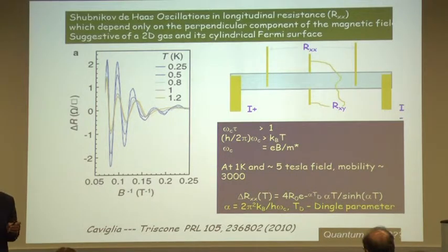But there are certain constraints under which you will observe these oscillations. And those constraints are decided by this condition, omega c tau, where omega c is the cyclotron frequency of the electron and tau is the elastic scattering time. It must be greater than 1. That puts a condition on the magnetic field, B. And also, you have to have this energy scale. This energy must be greater than the thermal energy k_B T. And all these conditions are satisfied roughly around 1 Kelvin, 5 Tesla field, when you have a mobility of about 3,000 centimeters squared per volt second. So very low temperature, high mobility samples will show you clean Shubnikov-de Haas oscillations.